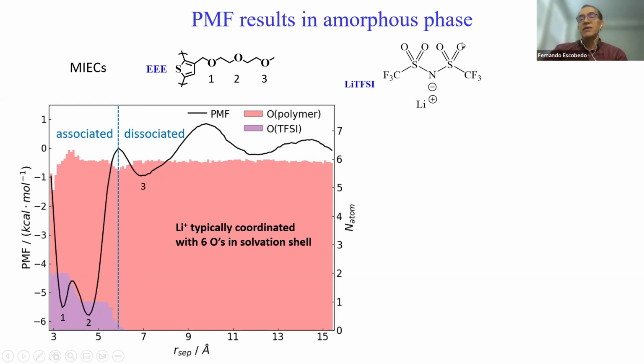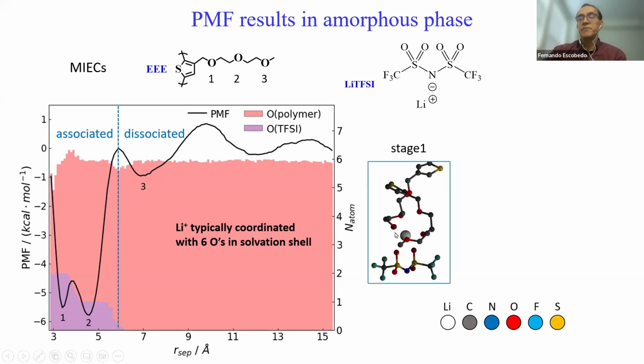So you see that the TFSI anion contains a number of oxygens, and they also tend to associate with the lithium. So you can see that initially they have significant association, of course, with the anion that later goes away as you separate the 2. But these different minima are very meaningful because they are telling you that there are some sort of metastable states, right? So the first minimum, 1, corresponds to the moment where the lithium ion, which is shown here by this sort of whitish bit, this larger bit here, has 6 oxygens coordinating, but 2 of them are coming from the anion. So these 2 down here, they are important.